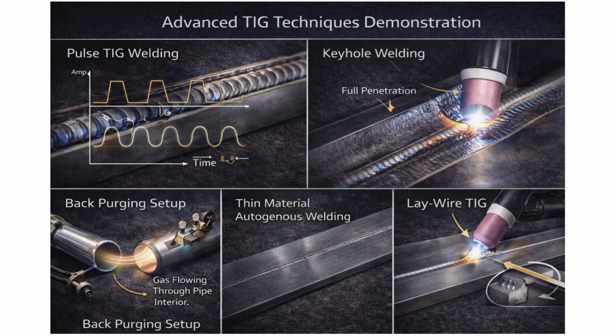Back purging is essential when welding materials like stainless steel and titanium. You flow inert gas on the backside of the weld to prevent oxidation on the root side. For autogenous welding, you don't add filler metal at all, you simply melt the base metals together. This works on thin materials and creates minimal weld reinforcement. Some welders use advanced techniques like cold wire or hot wire processes for increased deposition rates while maintaining TIG quality.